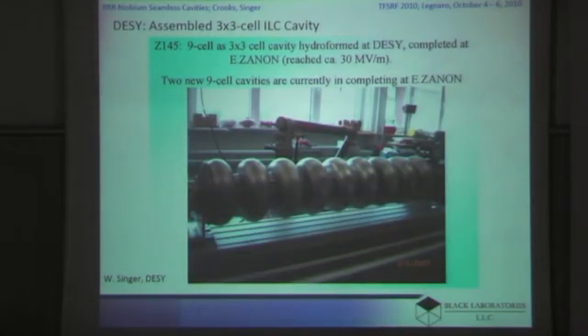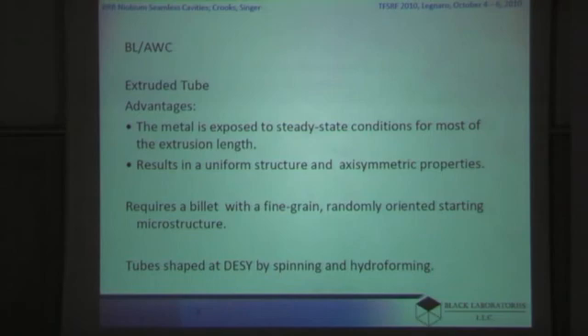The best result so far from the DESY work is shown here in its welding stand, I think, at Zanon, and was a 9-cell cavity which was able to reach 30 megavolts per meter accelerating gradient after electropolishing, I think. The method we chose, using extrusion instead of spinning or deep drawing for the tube, the intention was to give us a long tube with uniform properties, which can be done with the extrusion, providing we're able to maintain a fine structure through the extrusion. A fine structure and also a crystallographically weak texture so that it gives us uniform properties.